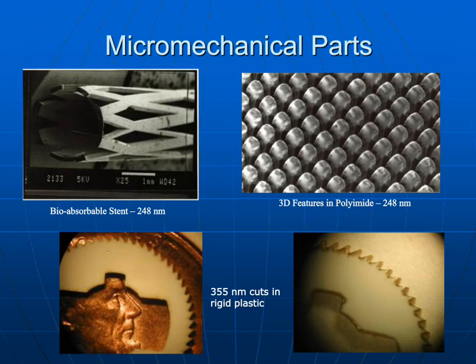On the upper left, you'll see a bioabsorbable stent. These bioabsorbable stents are made with short wavelength and/or short pulse length lasers because they're actually heat sensitive since they're made to dissolve in the body. So if you have any heat in the laser process, you can't make a bioabsorbable stent. They're very sensitive to heat.